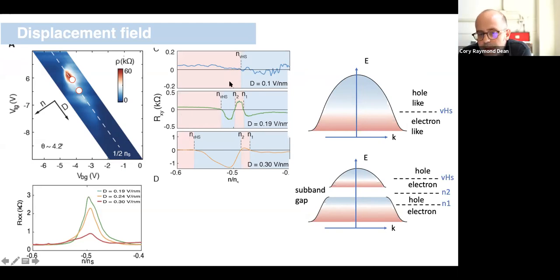Now, the other thing I want to point out here is that between panels 2 and 3, for example, the relative positions of what we call N1 and N2 are not changing that much, but the relative position of what we call N Van Hove singularity is changing more dramatically. And we interpret this response as indicating that this Van Hove position is something like the intrinsic Van Hove position in the band, whether or not there exists a spontaneously opening gap. That's our interpretation of this value.